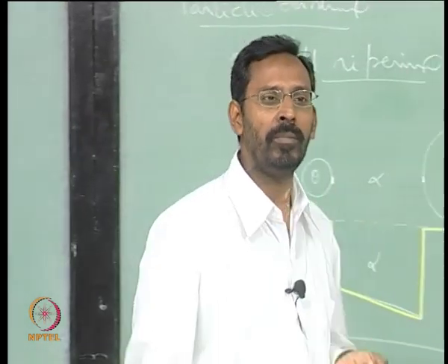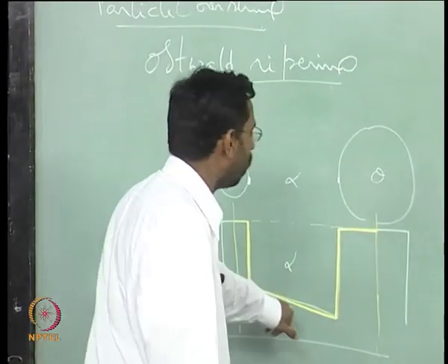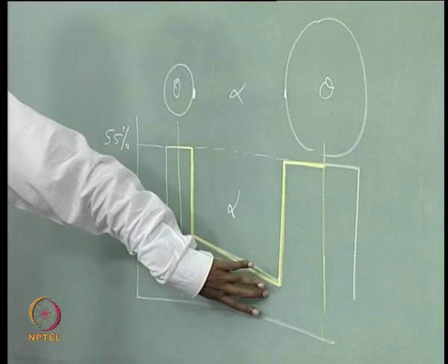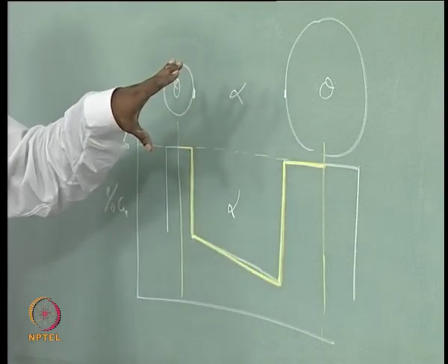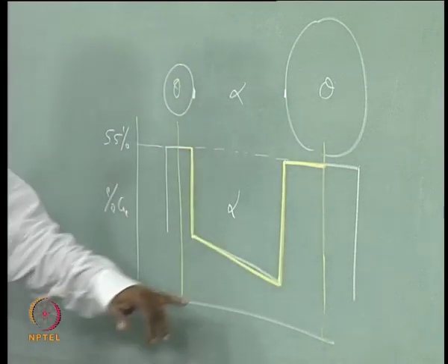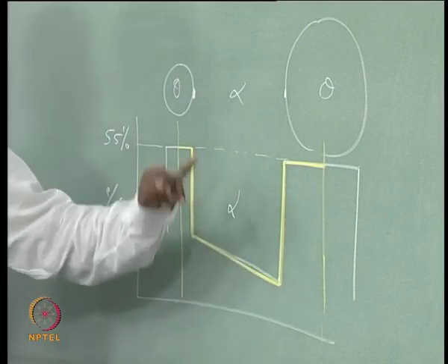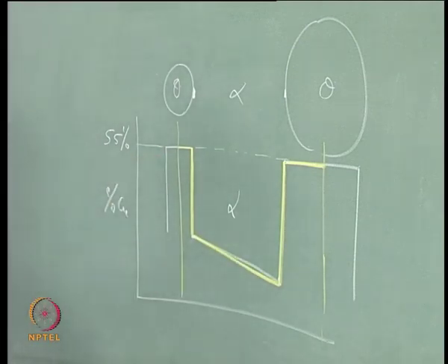diffusion, you will always have a flux at any given temperature, because flux J is equal to minus D into dC by dx, and that dC by dx you can see here, the x is nothing but the interparticle distance. Once you know the interparticle distance, you can talk about what is the dC by dx, and at any given temperature D can be known. So, you can actually see, and what is the result of this diffusion?